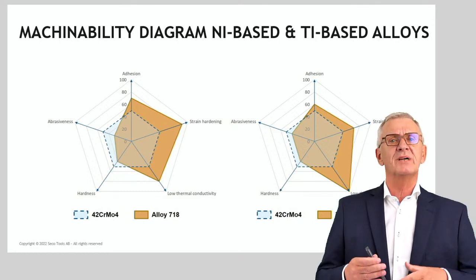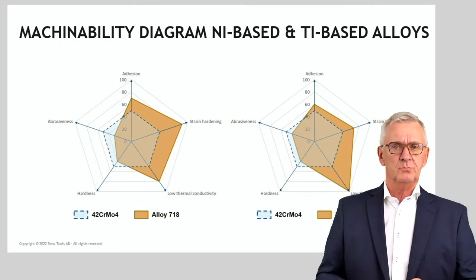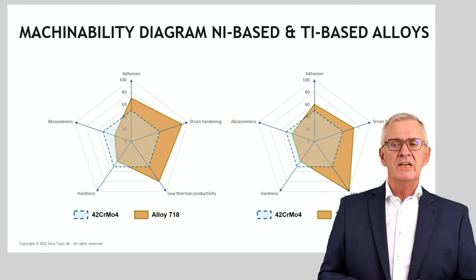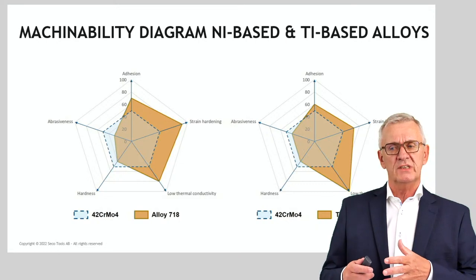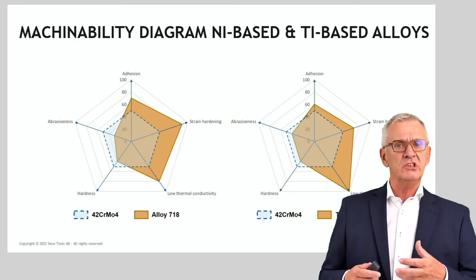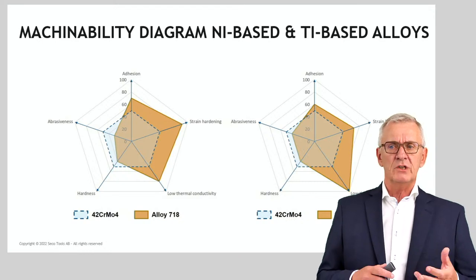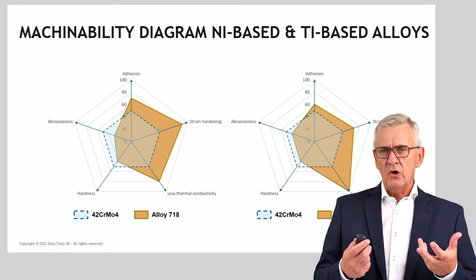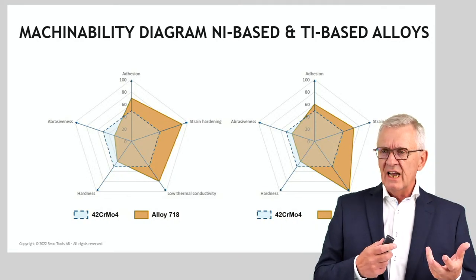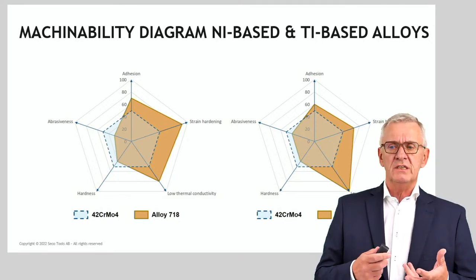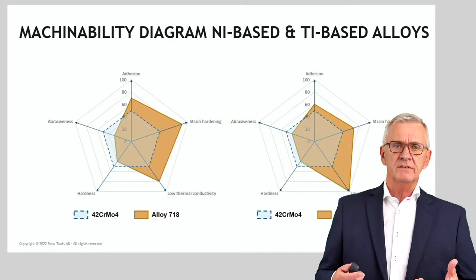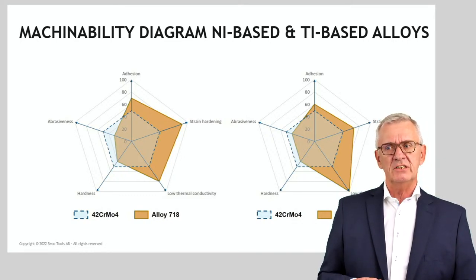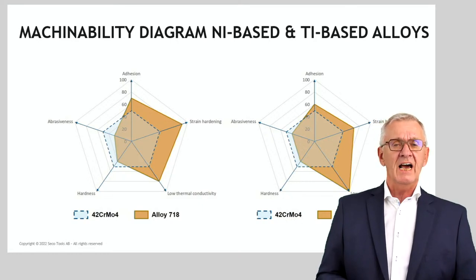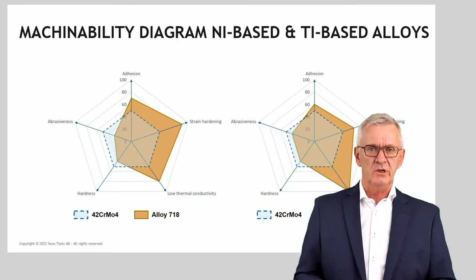But the main thing here is what you see, the blue area in the middle with the dotted line around it, represents the impact of those properties on the machining process when you machine a reference steel material. And the orange part, the yellow part, indicates how these properties are in alloy 718. And then you see differences. To the left side, when we talk about abrasiveness and hardness, those properties have a lower impact on machinability in case of alloy 718. However, if you look to the right side, you see that adhesion, strain hardening, and low thermal conductivity have a much higher impact on the machinability of the material.